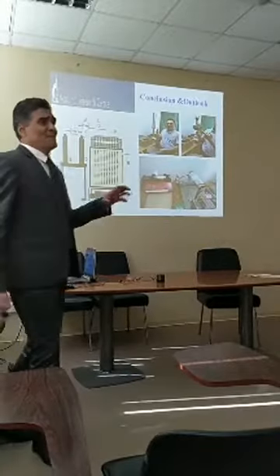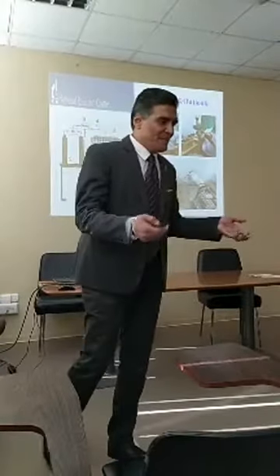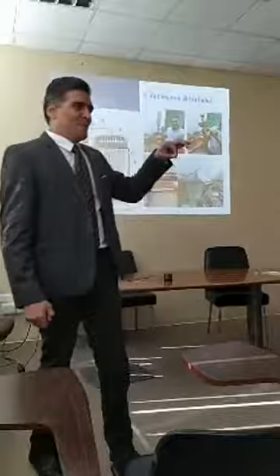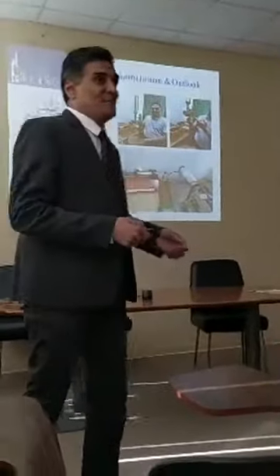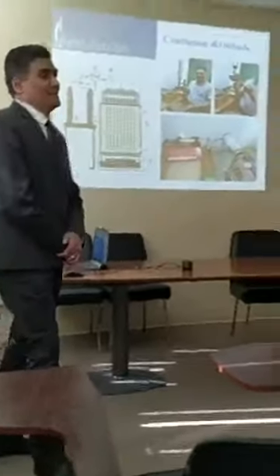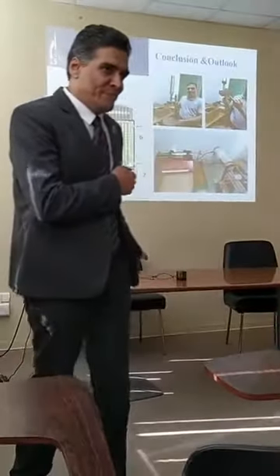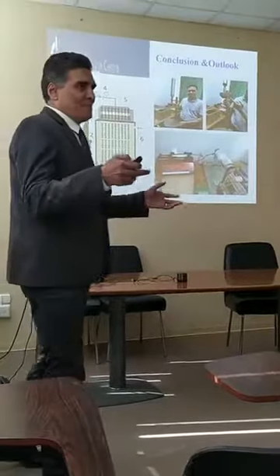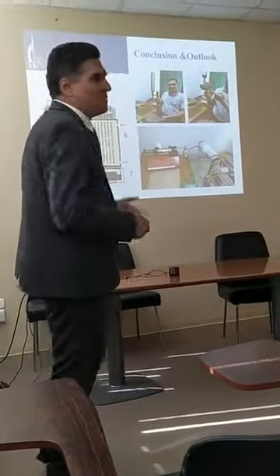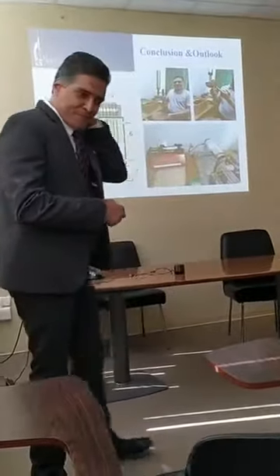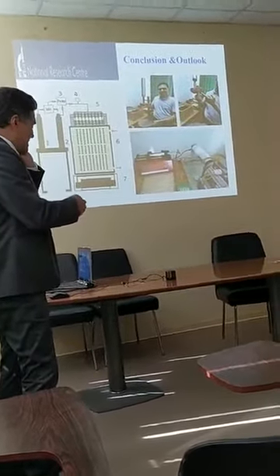For example, we are now working on an instrument to make not a mass production, but semi-pilot microsphere. We can produce something like 2 kilograms in 1 hour because we work only with the tip, and now we can produce some amount of this microsphere to be scaling up our work. And then we have a handmade electrospinning technique. We can produce instead of a sphere, we can do it like fiber. Okay, I know that there is an institute here that has already developed a more modern technique than this, but it's handmade.